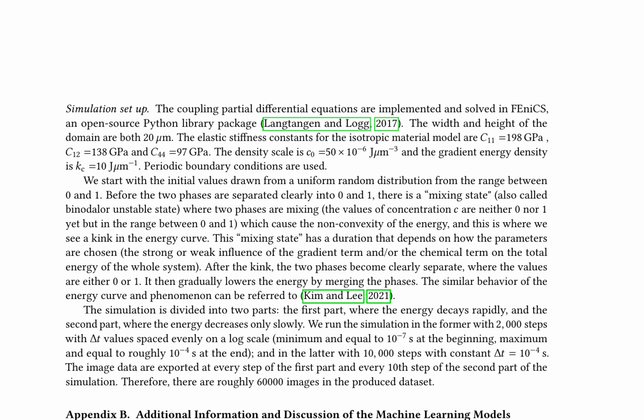The simulation setup for the phase separation process in a binary alloy system utilizes the FEniCS library to solve the coupled partial differential equations. The domain size is set at 20 micrometers in both width and height, with elastic stiffness constants C11, C12, and C44 defined as 198 gigapascals, 138 gigapascals, and 97 gigapascals respectively. The density scale C0 is 50 times 10^-6 J μm^-3, and the gradient energy density Kc is 10 J μm^-1.